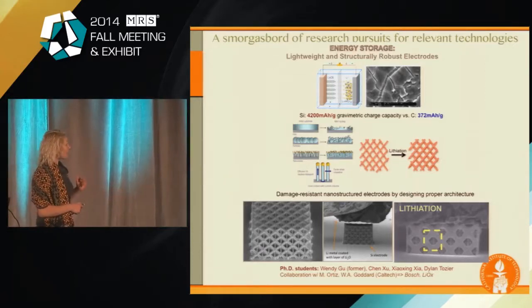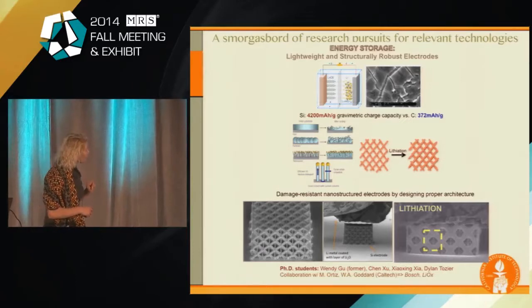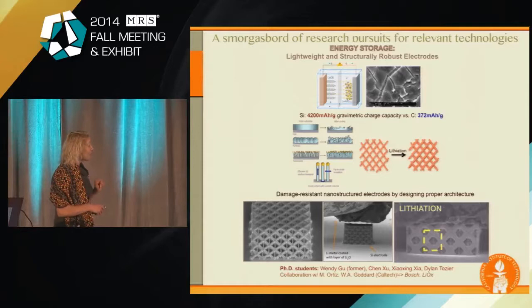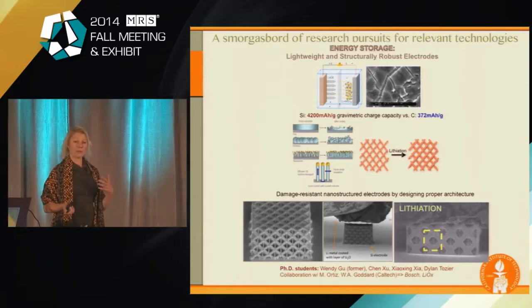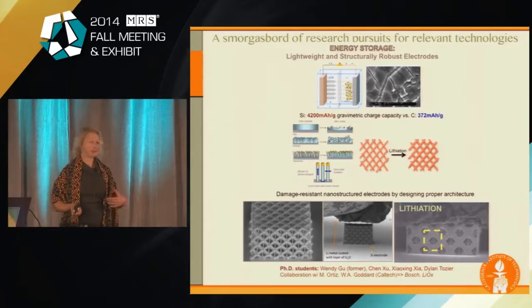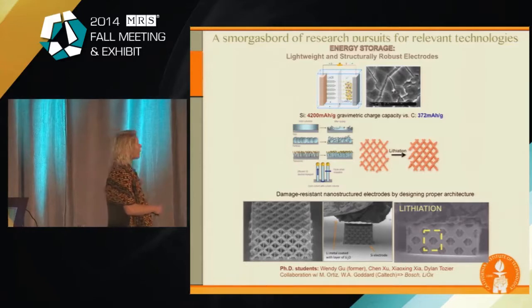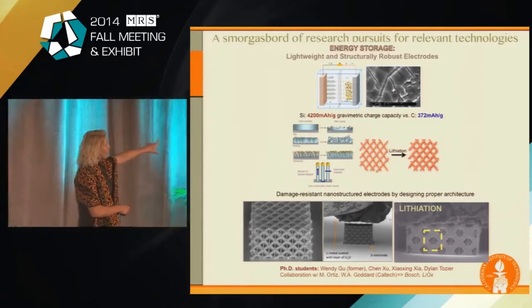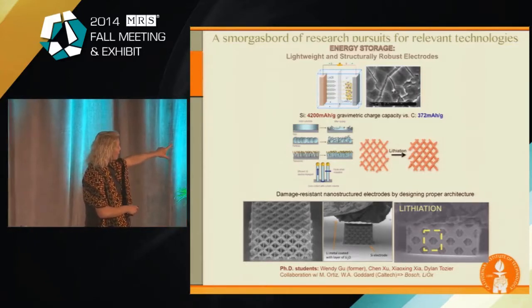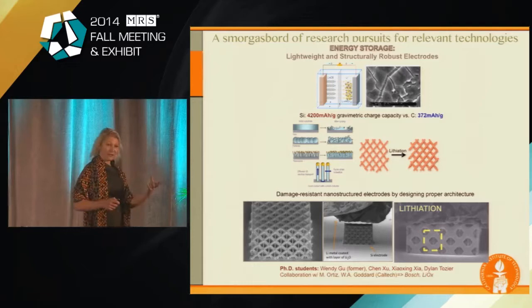So it turns out that for lithium-ion batteries, it would be much better to use silicon, which has about an order of magnitude greater storage capacity than graphitic carbon, which is what's being used right now for the anode materials in the lithium-ion batteries. So this is a schematic of how a battery cell operates. Well, it turns out that if you were to replace this anode with silicon, this is what you would see. This is a thin silicon film that's very much cracked after you lithiated it.